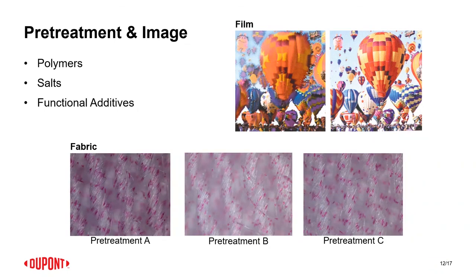Similarly, in textile applications, pretreatment can have a massive effect. These 3 samples here are all the same ink, the same fabric printed under the exact same conditions. Really, the only difference is the particular pretreatment formulations that were used. And you can see very clearly, right, the clarity and the sharpness of the line that's printed. If you think about that in a larger image, if you were to take a step back from the magnification, it's not just going to affect your line acuity and how sharp your image is, but it also could give you a brighter color, or what appears to be a stronger color strength, because now you've got more of the ink sitting up on the fabric.